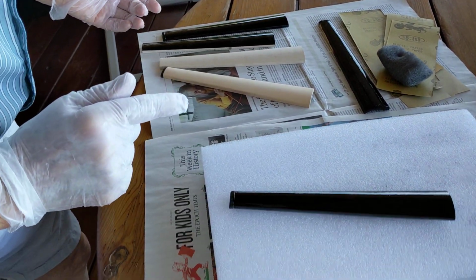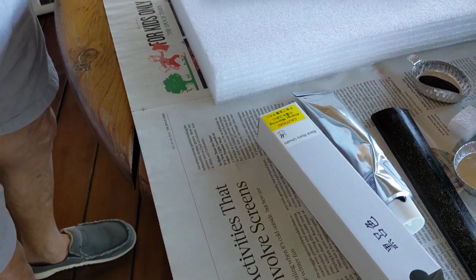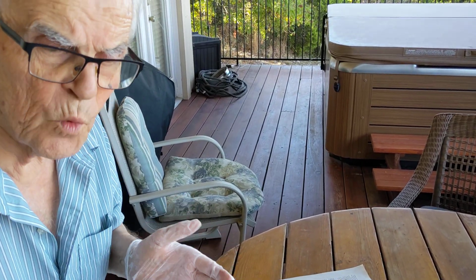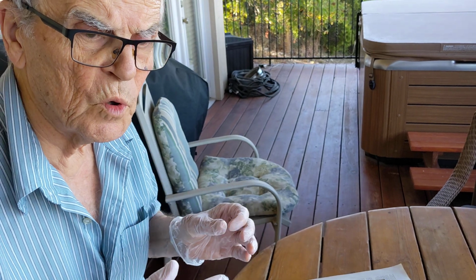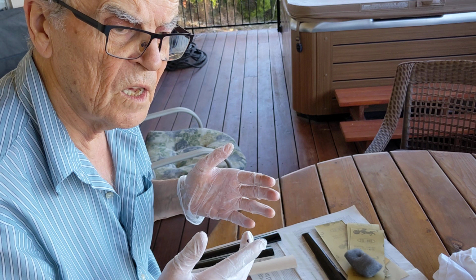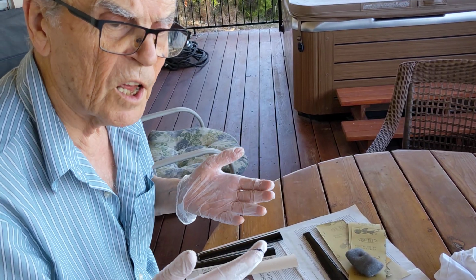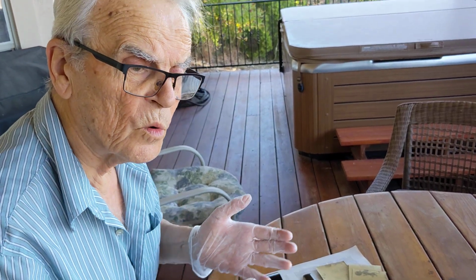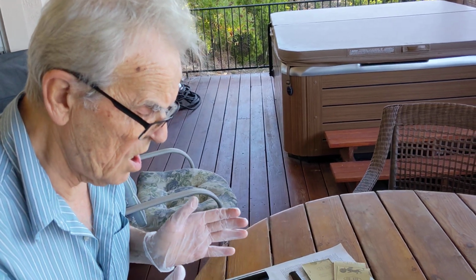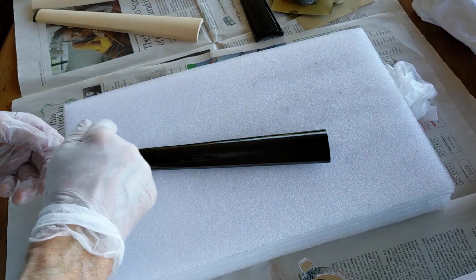And then you have a strong fingerboard whose surface repels water. The important thing about Urushi, when it polymerizes, it is hydrophobic. It does not absorb the moisture from the fingers of the player, and for that reason, you don't form the channels, the indentations that you normally get in fingerboards. So the lifespan of the fingerboard is made much longer.